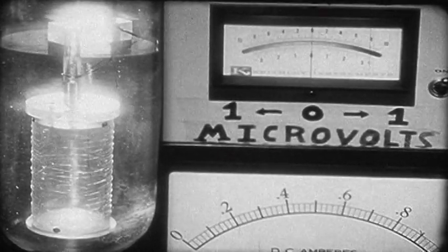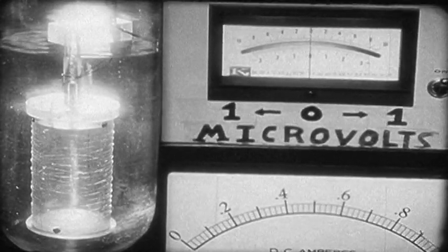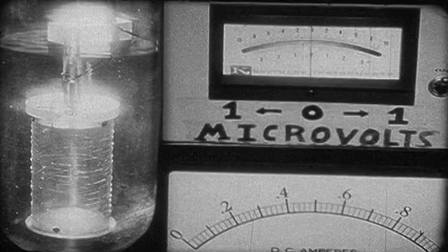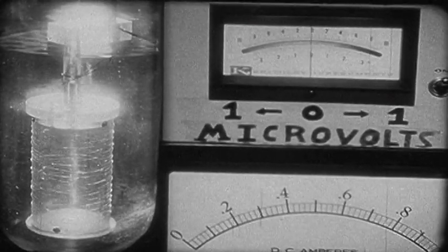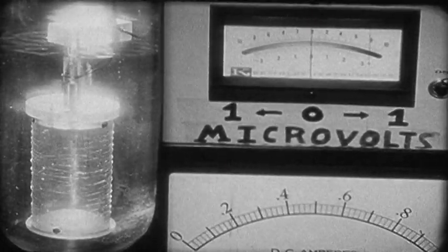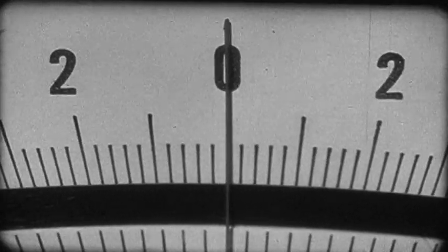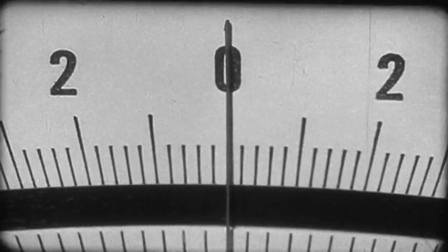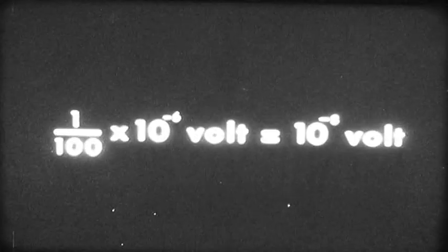The result important to us here is that after this transient, the potential drop is 0 again, while the current is 1 ampere. Remember that at this current, above the transition temperature, the voltage was 25 millivolts. It is now 0 to within the estimated error of this scale, which is about 1/100th of a microvolt. The voltage across the wire is not more than 1/100th of a microvolt while it is superconducting. Above the transition temperature, it was 25 millivolts. Therefore, the resistance of the wire has dropped on transition by a factor of 2.5 million or more.